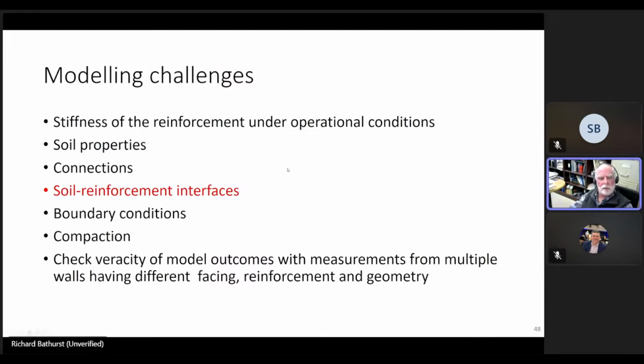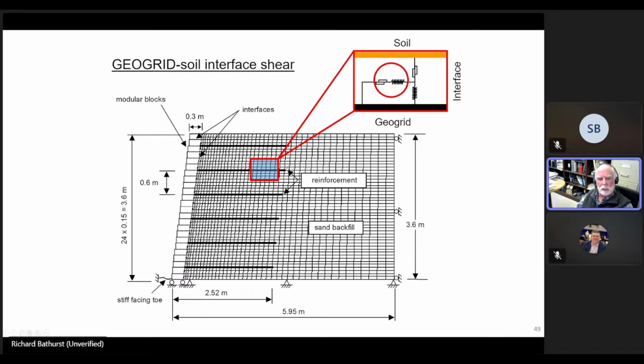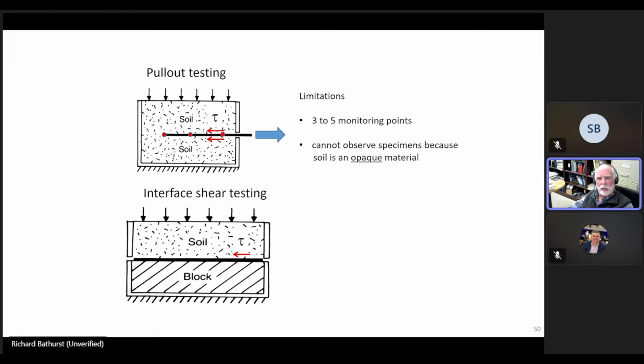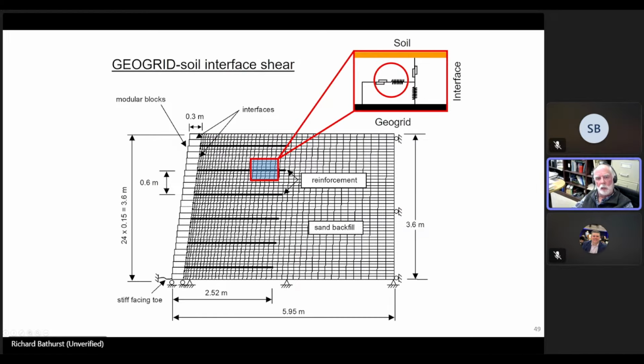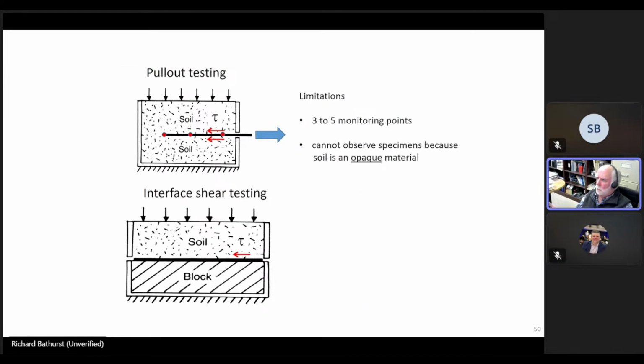Soil reinforcement interfaces. So when we look at our numerical model, we have to model the transfer of load between the surrounding soil and the reinforcement layers. And we usually use some sort of interface model with shear stiffness springs and normal stiffness springs. But it's often difficult to back calculate what those values are from simple element tests, including pull-out tests or interface shear testing, because you have limited monitoring points and you can't see anything because the soil is opaque.